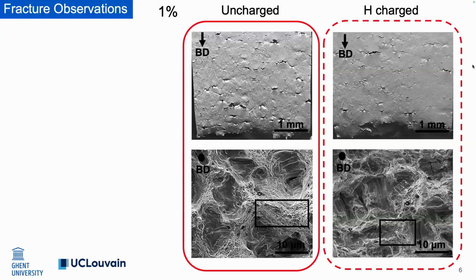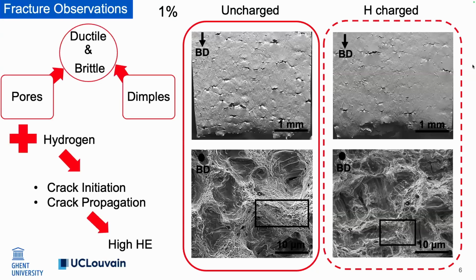For the second batch, we can see there is some coalescence of cracks in the images above. Also, after charging, the fraction area of ductile mode decreased by hydrogen charging, and the brittle features are more pronounced in hydrogen charged samples. So here we have a mix of ductile and brittle fracture because of the presence of pores and also dimples. We can infer that hydrogen triggered the crack propagation, and the pores act like a crack initiation site in this material. This is the reason why hydrogen embrittlement in this material is much more significant than in the first batch.